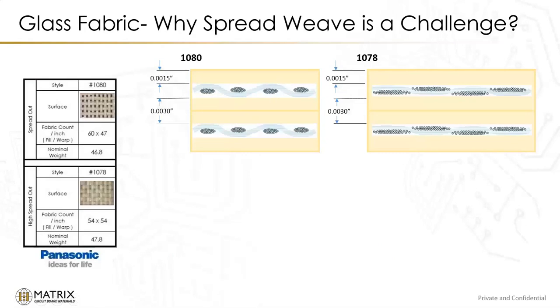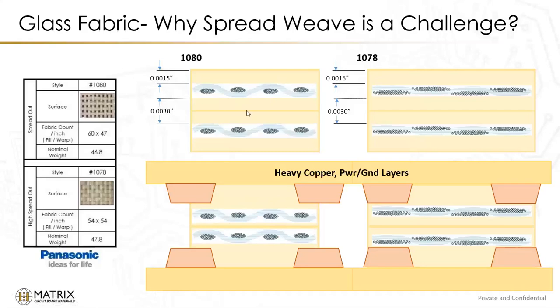But the concern, and the unintentional consequence of the spread glass, is that it doesn't really allow for the transfer of the resin. At 1080 and more open weave, we get more transfer of the resin through the glass, where we don't see that as much on the spread glass. It acts as a kind of filter that holds it together. You can see in my little diagram between these two, on the 1080 side you get more of a squeeze together, so the resin in between gets pushed to fill the heavy copper areas, where you don't get as much of that with the spread glass. It tends to hold the resin in between the plies. So that's why I think it's important to really consider the surface resin as the amount that you have available to fill.